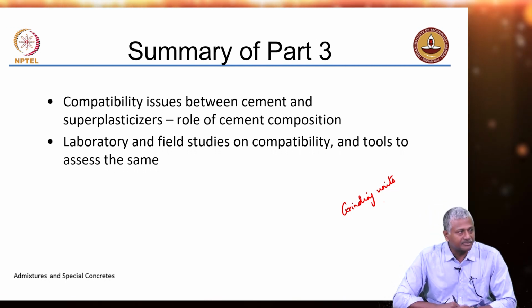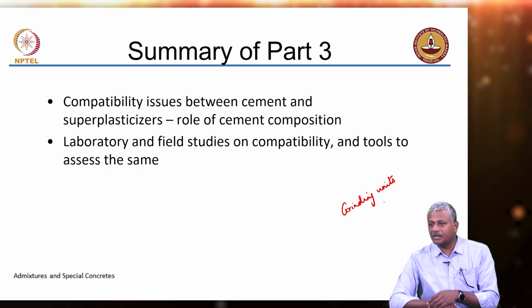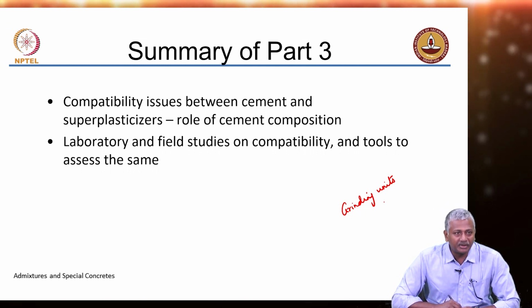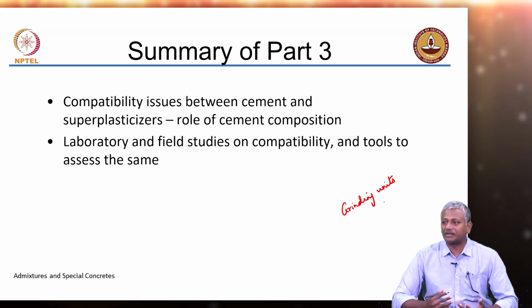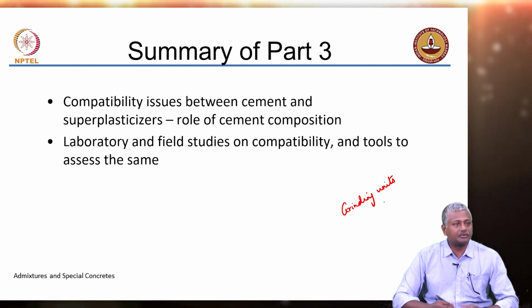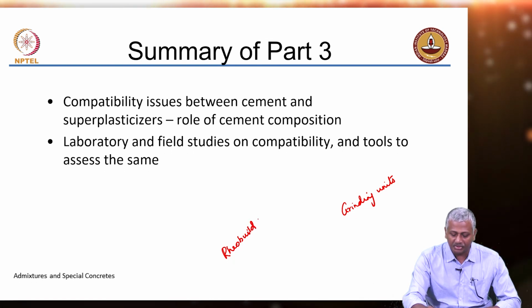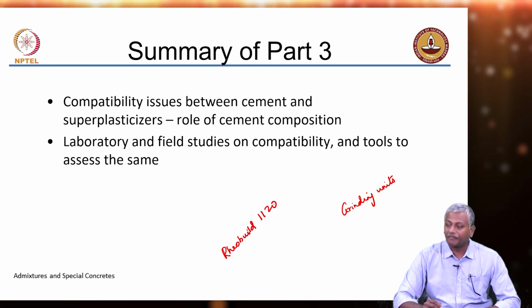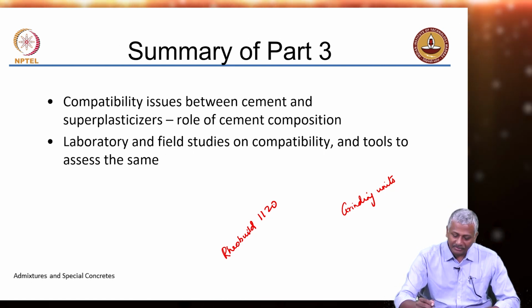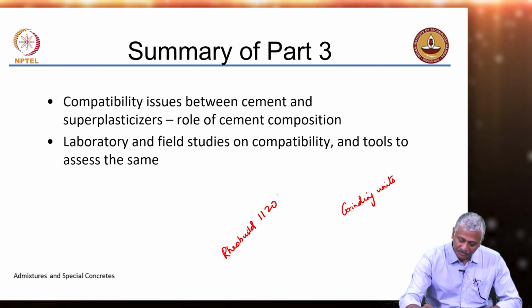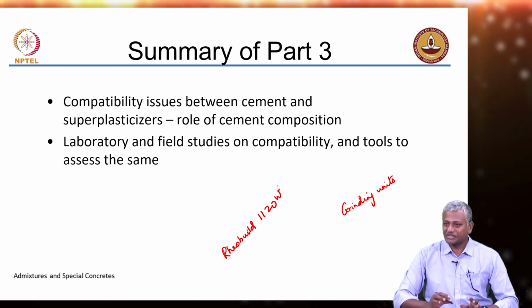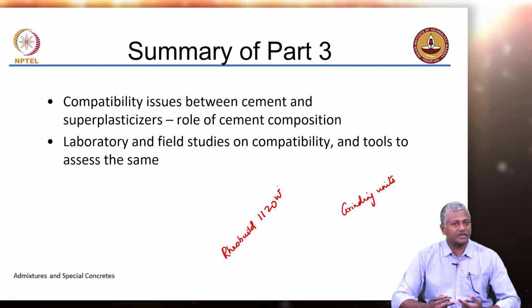Because of this, the admixture companies always have service people who run around between job sites. If there is a problem like this, they run back quickly to their R&D and get minor tweaks in the formulation done until their admixture actually matches the demand of a particular job site. So, the admixture formulations keep on changing. As a result, the same product may have 10 different types of formulations, right. For instance, one of the products that is commonly used is Rheobuild, an SNF admixture from Master Builders, Rheobuild 1120, right. In one job site it may have the 1120A, in another job site it may be 1120W. It is essentially the same compound, but it has been minorly changed so that it meets the demands of a particular job site.